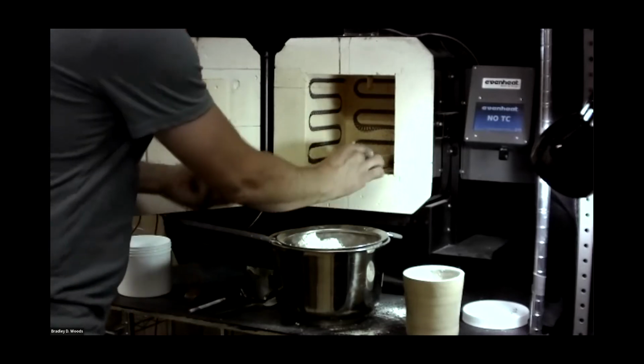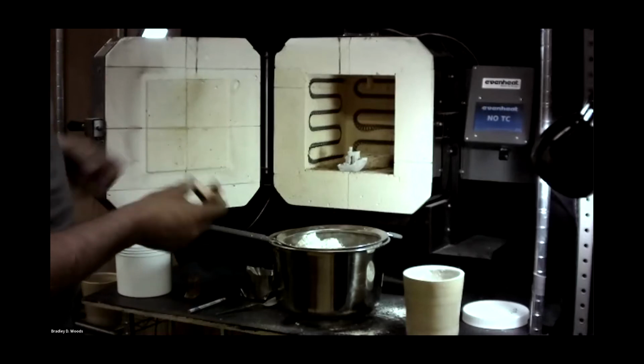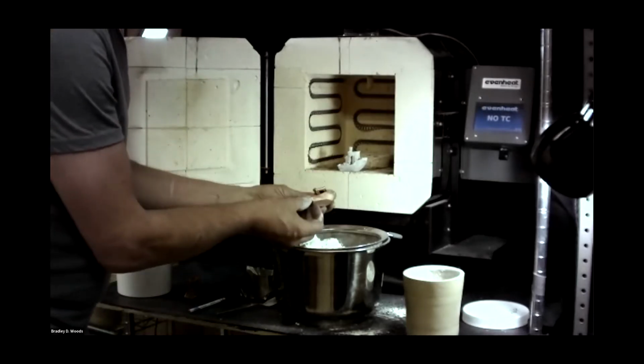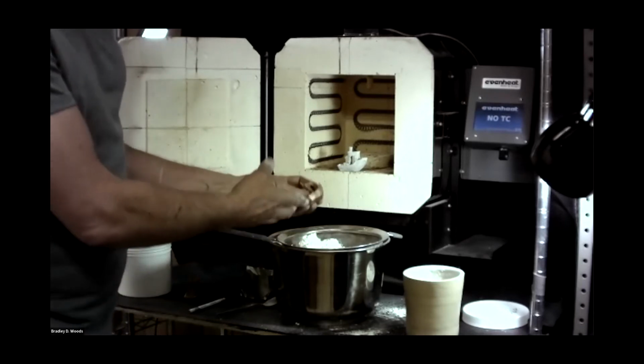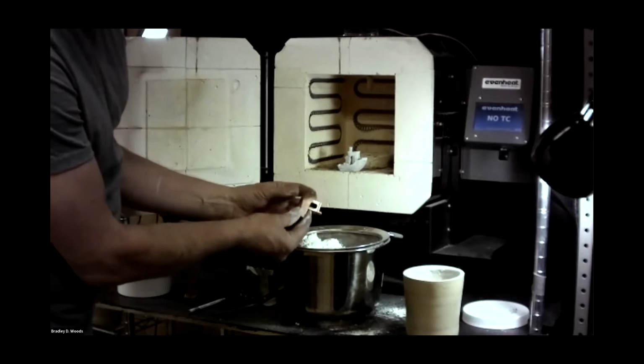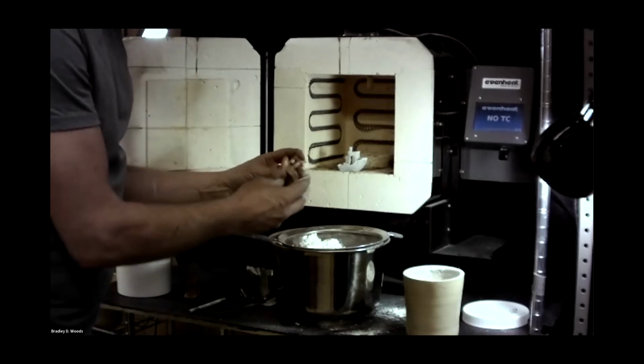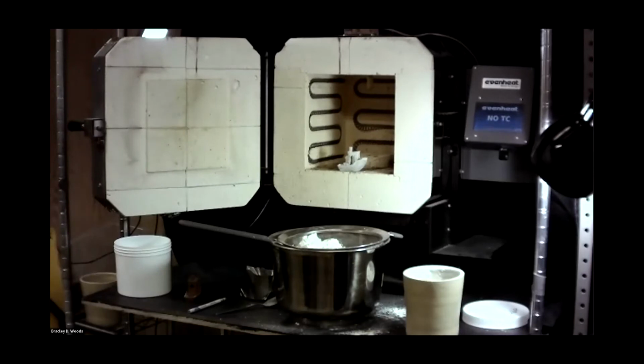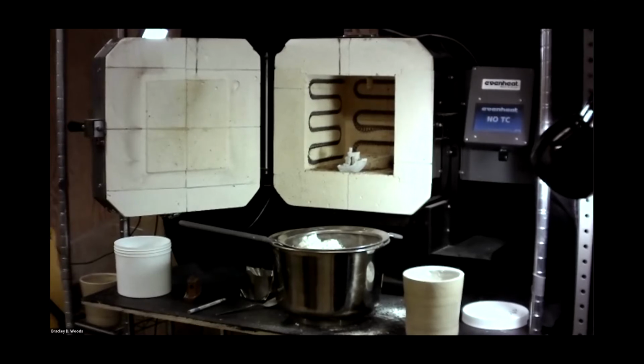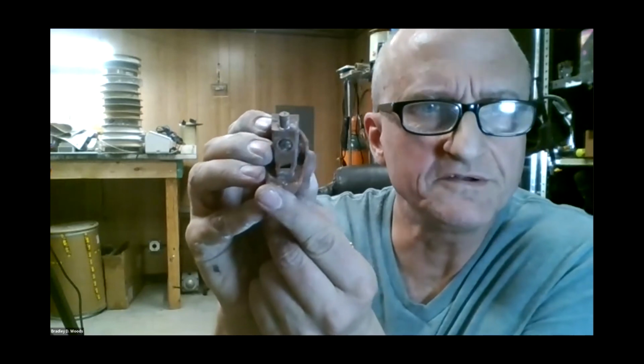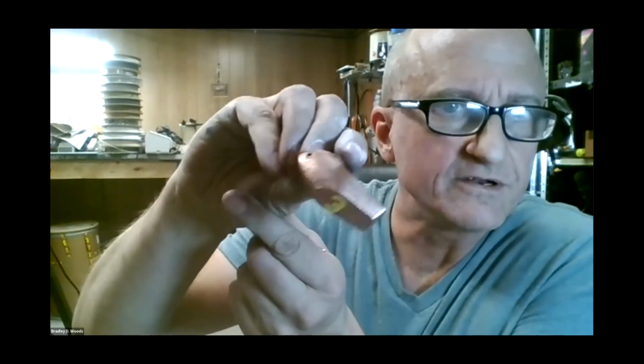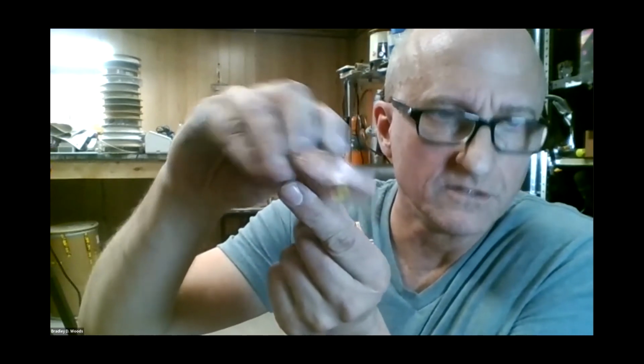So this is our sintered final part. And the next step is cleaning it up a little bit. This is a part. We need a better picture, but this is with about 10 minutes of work with a wire brush on a Dremel tool. I'll switch to my other camera. You can see it a little bit better. So this is what it looks like coming out. So let me show you that right now. So this is fresh out of the kiln, a freshly sintered part. The bottom of it, I have hit with the wire brush.